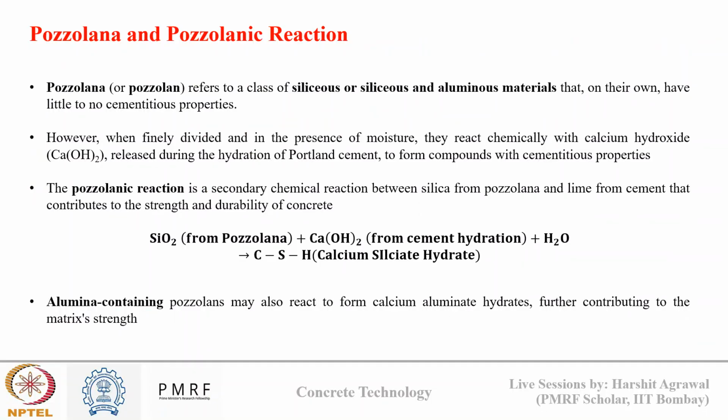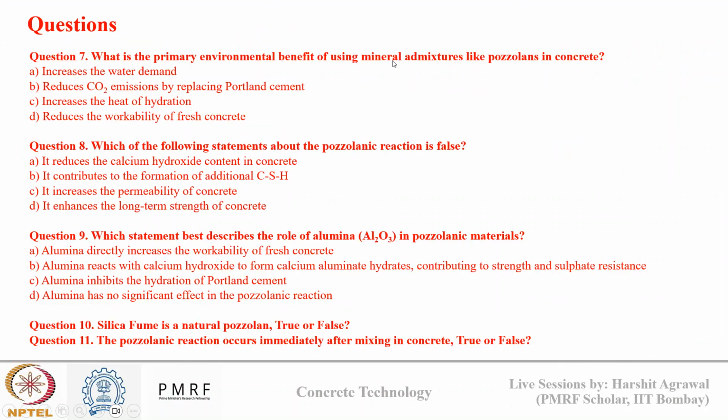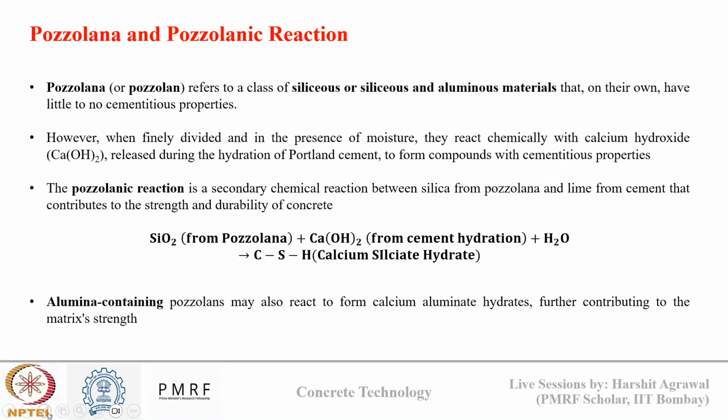These produced SCMs are all amorphous in nature, and this amorphousness was imparted in these SCMs either due to rapid cooling or due to grinding of the SCMs. Now, although they are amorphous in nature, they don't react with water on their own. It is not like when I add water, they will form hydration product. No, they are not able to react with water directly.